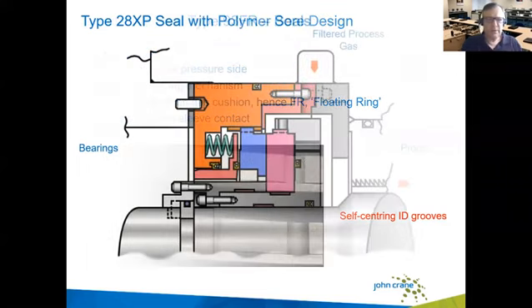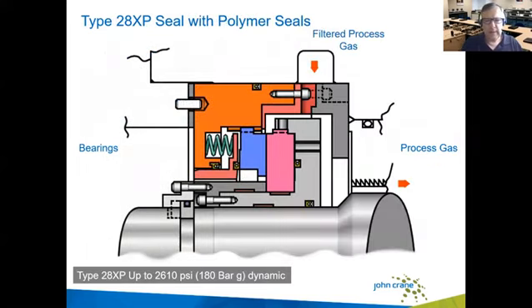Now, as I said, pressures have been forever increasing, and we had a problem with pressure once we reached a certain condition. So we had to redesign the dry gas seal to cope with the higher pressure demands. And it meant changing this area around the back of the primary ring. As you can see now, the retainer is now being modified and has a polymer ring and a carrier design. We've actually replaced all of the O-rings on this seal with polymer rings, polymer seals.